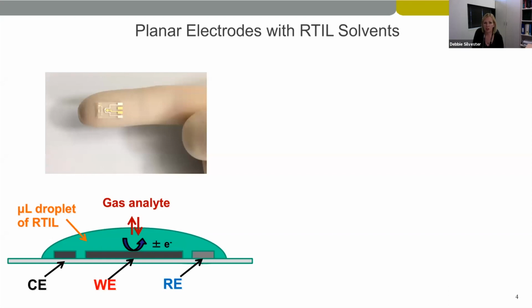So obviously we're trying to now change the design of these sensors and use different materials. And we're very interested in ionic liquids because of all the application that Jenny mentioned earlier, and particularly they're non-volatile, so we can use just a tiny volume, so a microliter droplet or less of the ionic liquid. So we have our planar device, and then we drop 1 or 0.5 microliters of ionic liquid over the 3 electrodes. So we have our gas continuously flowing, and we have a partitioning step where the gas goes into the liquid phase. And then once we have equilibration, we apply a potential to oxidize or reduce that gas.